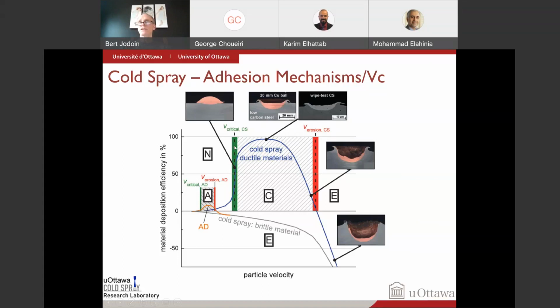This is what we call in cold spray the critical velocity. That's where the velocity is fast enough that most particles are able to break the oxide layer of the substrate upon impact, and will start to stick. And this deposition efficiency, when you go faster and faster, you get more and more in terms of percentage that will stick to the substrate. However, things are never that easy.